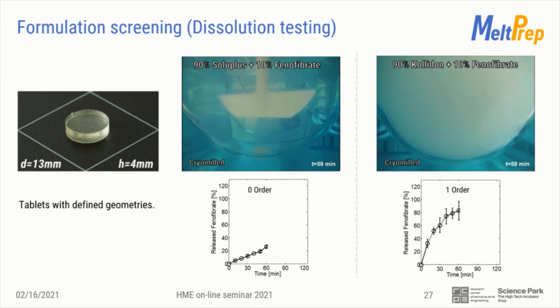With Soluplus, you have the zero order release. With PVP, you have the first order release, the fast one. And this is a very nice way to test the performance of your formulation. You can use this information and then tailor the surface area of your dosage form to your requirements.